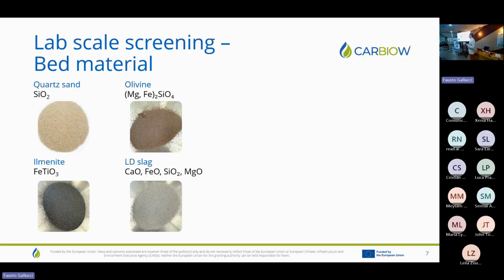For our bed material screening, we first applied quartz sand, which is an inert bed material and is very commonly used in fluidized bed technologies. Then we also used olivine, which is often used because it has some catalytic tar cracking abilities. And the lower ones are the oxygen carriers. There we have ilmenite and also LD slag, which is a residue from the steel industry.